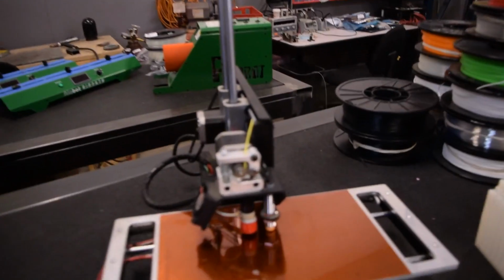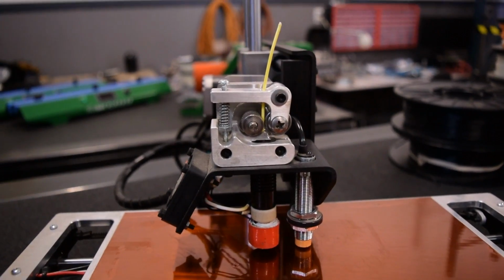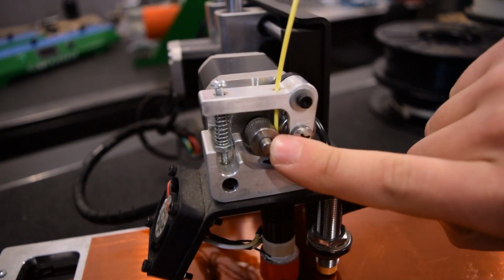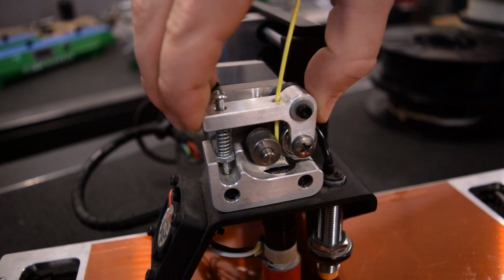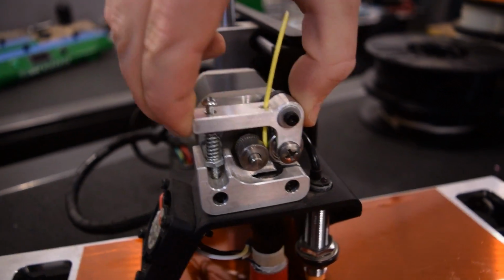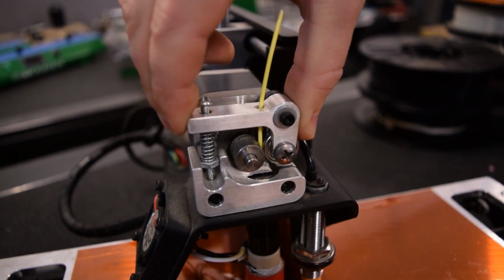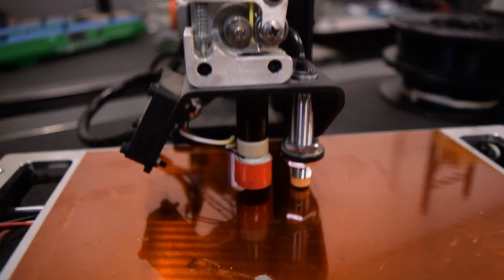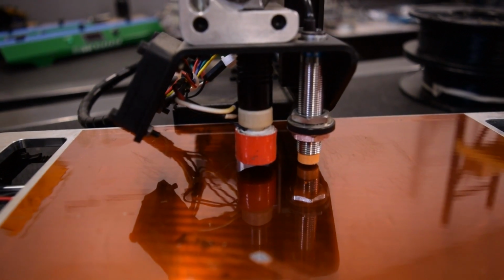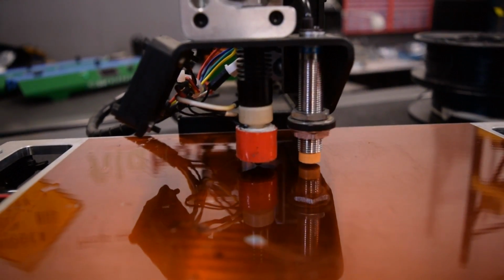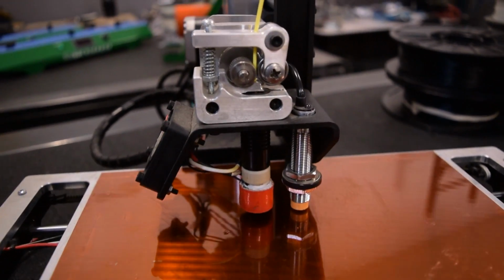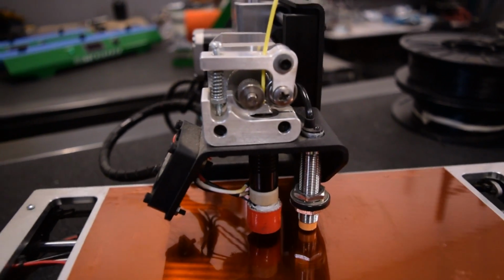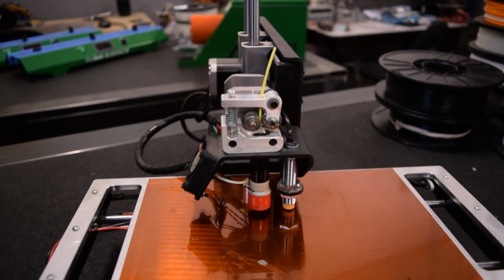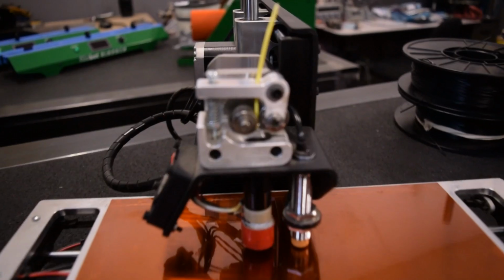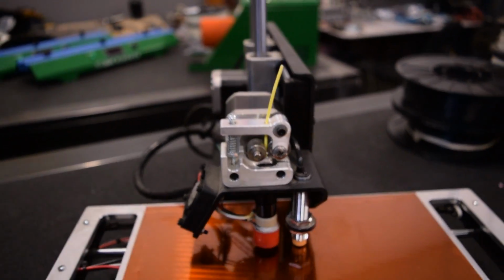So the drive system on most 3D printers is a little gear piece, and that's tensioned by a little bearing against the filament, and that gives the pressure that pushes your filament down through your hot end. It's exactly like a little hot glue gun basically. So if your nozzle clogs, your filament just won't push down. It'll actually wear through it and cut it off.